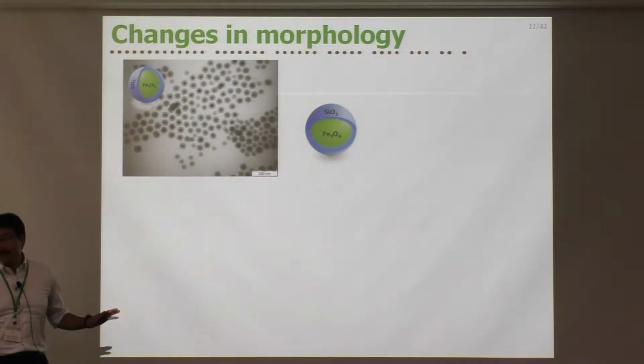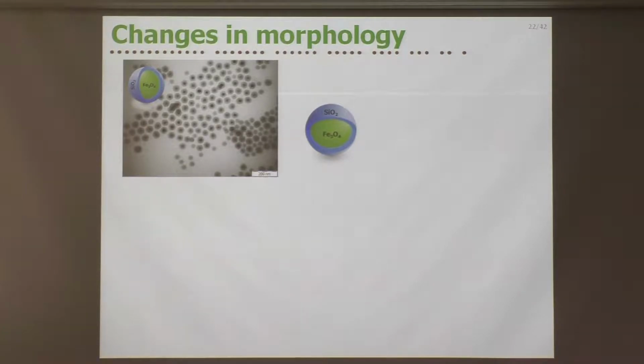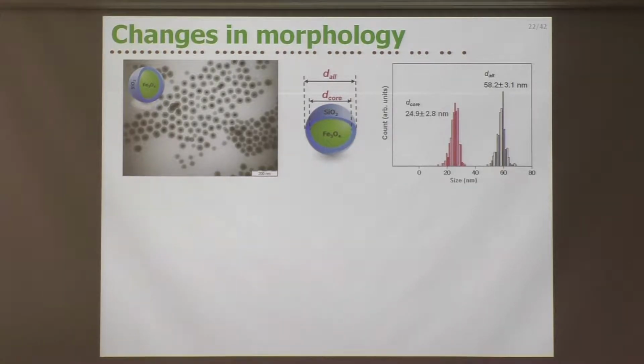In this slide I'd like to talk a little bit about the details of the changes in morphology. Here again is the TEM image of the sample before reduction. The sample before reduction has 2 characteristic sizes: one is the size of the core, D core, and the other is the overall particle size, D all. The D core is about 25 nanometers, and D all is about 58 nanometers.